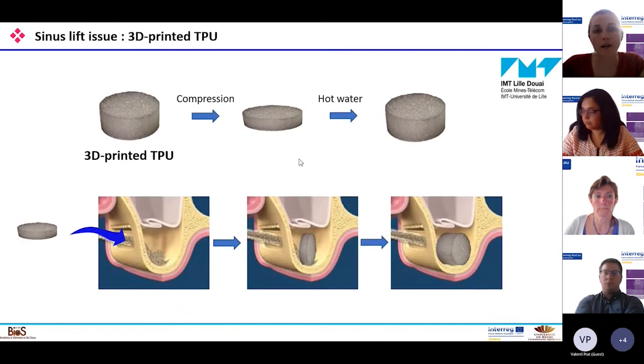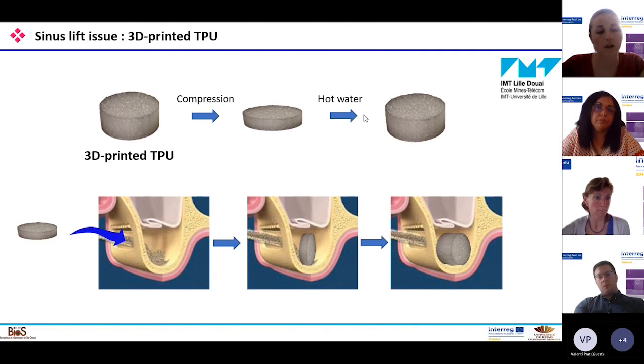So at IMT, they managed to print TPU scaffolds which were able to be compressed, and then with hot water, they go back to their first shape. So our idea is to compress the scaffold, put it in the bone defect, and then the scaffold should be able to redeploy itself and occupy the whole bone defect.